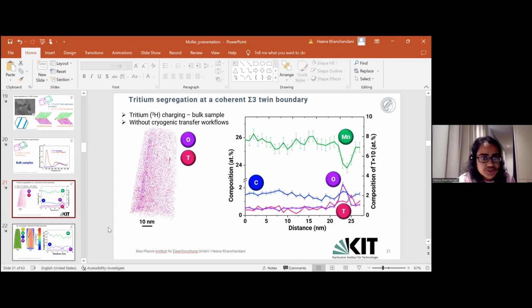So this tritium charging was done by the tritium gas charging method, so it was a 500 ppm tritium and hydrogen mixture. And this was a gaseous mixture. So this charging was done at 4 bar of pressure. And it was also done at high temperature, 70 degrees Celsius for 6 hours. And this grain boundary also has this manganese depletion.